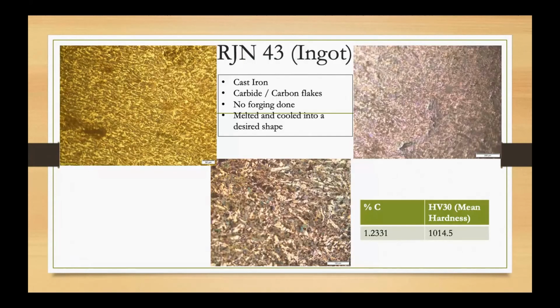The next sample that was very important for me was basically an ingot. And why I'm saying it's important, because this proved that the later stage of melting was done at this site itself. I'm saying melting and not smelting, because for smelting you need a proper furnace. You need to take the temperature above 1130 degrees Celsius, where we do not have a burning patch.